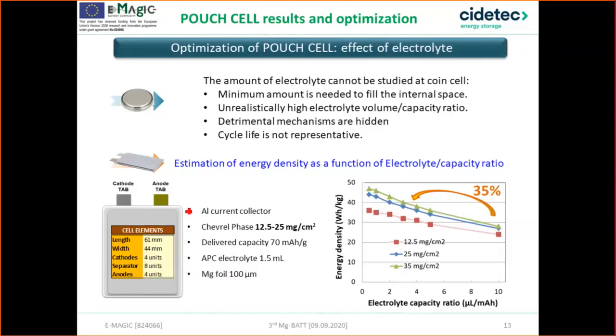In the lower part of the slide, we estimate the effect of the volume capacity ratio if we could diminish this parameter to values close to the ones used in lithium-ion battery. We can boost the capacity, the energy density of the pouch cell up to 35%, which is a significant value.